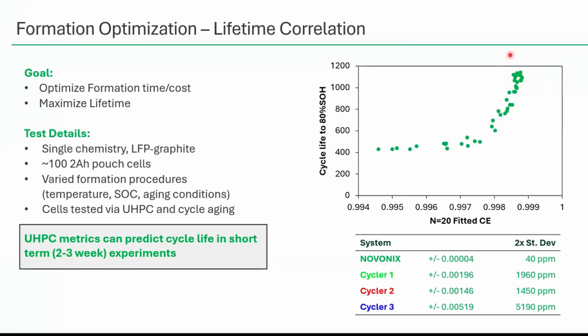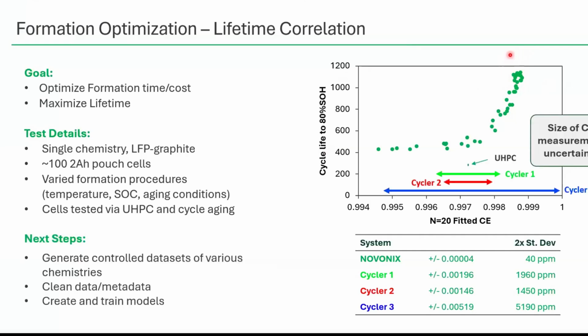To drive home why this is really possible with UHPC, I'm going to put on the error bars of the coulombic efficiency measurements I showed earlier from other cyclers, these are the brands that are very common in labs across North America. The error bar on UHPC is about as big as one of these points, so we're really going to be able to take the next round of optimization, do the UHPC testing, find this final coulombic efficiency or fade or slippage value, and correlate directly to where that's going to land in cycle life and determine if it's even worth testing that cell.